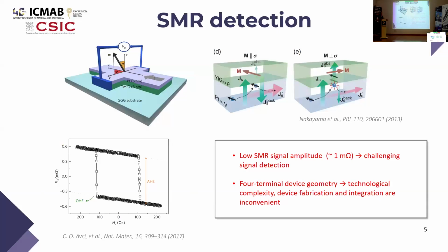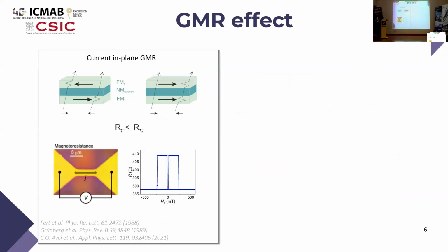However, if we want to use those materials in spintronics, we have to know these two things. We have to be able to electrically control and also detect the magnetic states. So far, people mostly use this method of detection, spin Hall magnetoresistance detection. However, it's very limited because the signals here are pretty low. And also, in order to detect the signal, we need this four-terminal device, which is quite impractical from the technological point of view.